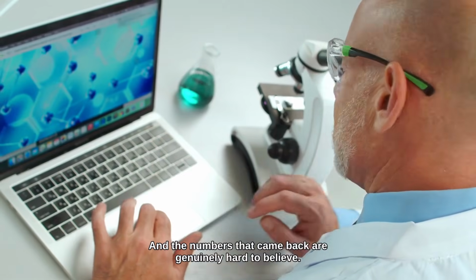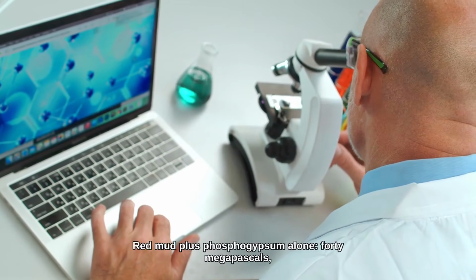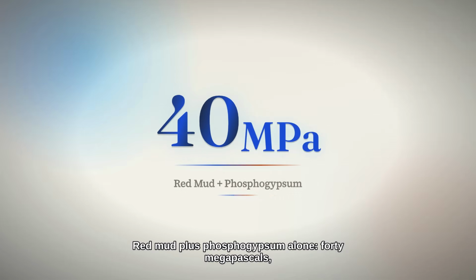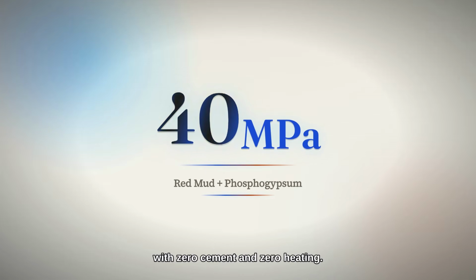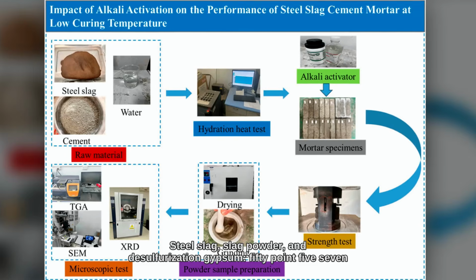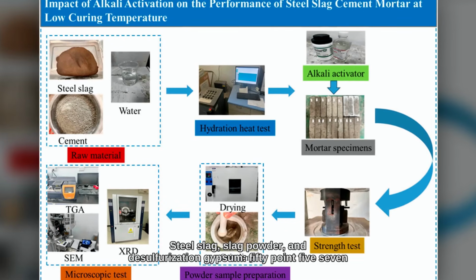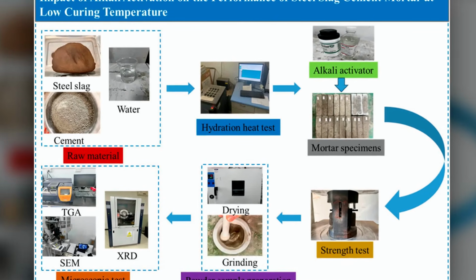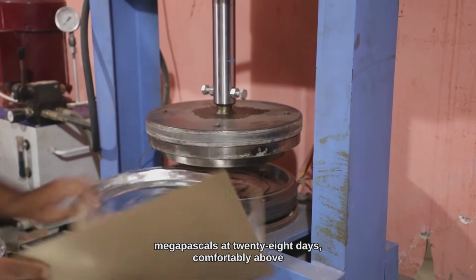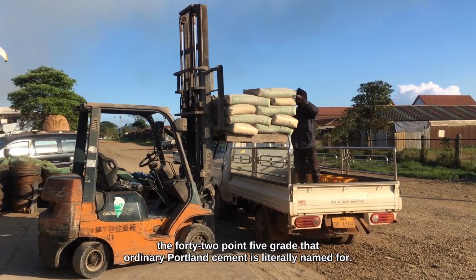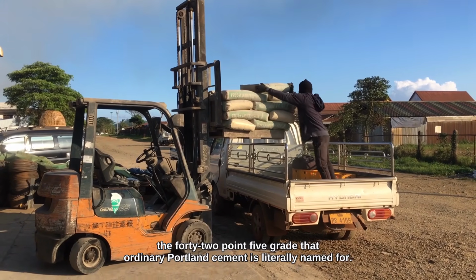And the numbers that came back are genuinely hard to believe. Red mud plus phosphogypsum alone, 40 megapascals, with 0 cement and 0 heating. Steel slag, slag powder, and desulfurization gypsum, 50.57 megapascals at 28 days, comfortably above the 42.5 grade that ordinary Portland cement is literally named for.